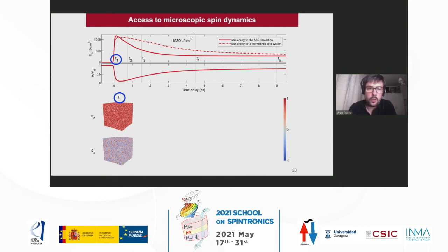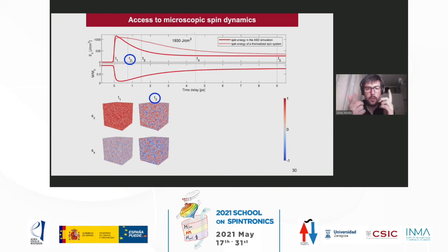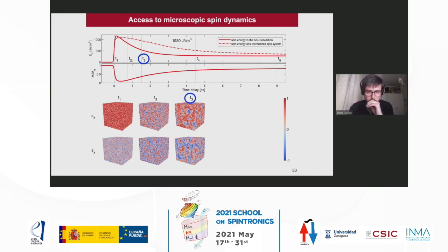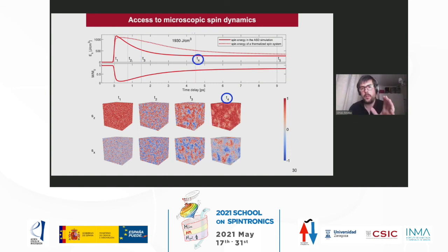And why does it increase energy? Because the system starts to get disorder, and this exchange energy increases. As we can see here, after we apply the femtosecond laser pulse, the spin components point to very different directions. But once the system starts to cool down, the spins prefer to be parallel, so they start to form magnetic domains with spins parallel to each other. As the system cools down further, all these domains start to align to the same direction, and at some point they go back to the initial state.